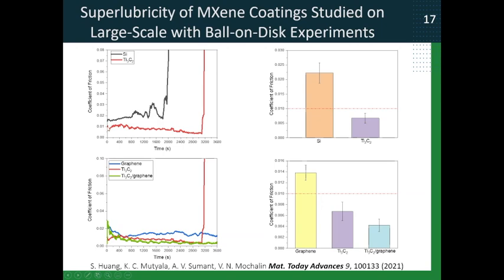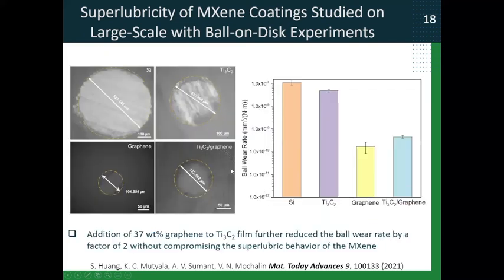But this value below 0.01 corresponds to superlubricity. So this is the coefficient of friction of this MXene film, and this is the coefficient of friction of just bare silicon. And then we also coated the MXene film with a film of graphene. And interestingly, we observed the same superlubric behavior. So now it's this green curve, but the film maintained its performance for much longer time compared to the original film. Again, this is the coefficient of friction of the MXene-graphene coating, still in the superlubric region, but now we also have other benefits.